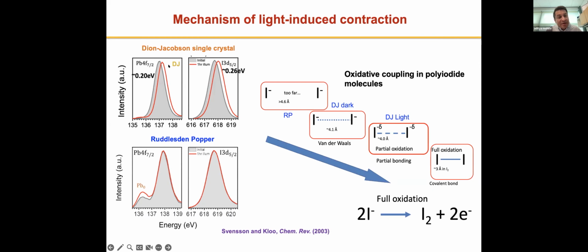And so we did this experiment on a Dion-Jacobson phase film, and you can see that the gray one here is the initial state of the film. Once we put light on this film, you see a shift in this curve by about 0.26 electron volts, blue shifting towards higher energies. The same thing happens also with the lead 4f orbitals, where everything shifts by a slightly lower amount. In contrast, with this Ruddlesden-Popper phase, you don't see any real shift. And so based on this, we came up with a model of what was really going on.